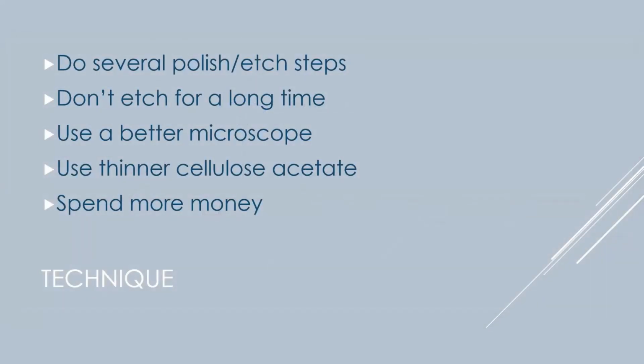The other problem, the reason why people can't find these things, is that if you do one polish and etch, which is normally what we all do in the lab, it won't detect these things. What you have to do is several polish and etches: polish, etch, polish, etch, polish, etch. It depends, but some people said you're removing smeared metal that covers over those very small voids, and now those voids all of a sudden start to pop up. So if you've not found them, maybe look at your polishing technique.